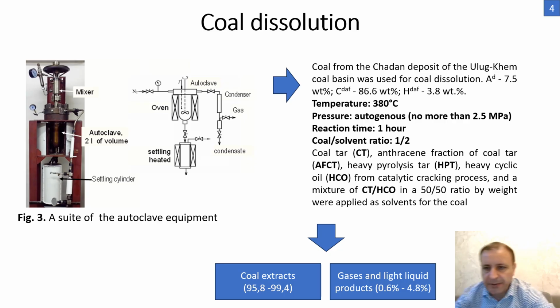The initial sample for the thermal dissolution was a bituminous coal from Chadan deposits of the Ulug-Khem coal basin. We used an autoclave equipment depicted in figure 3 for obtaining coal extracts via the coal dissolution process. The coal was ground previously to fines of less than 0.2 millimeters and mixed with the solvents to form a paste in a ratio of 1/3 coal to 2/3 solvent by weight.